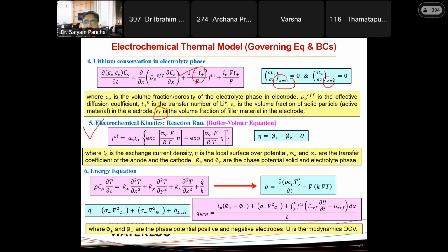And electrochemical kinetics, basically the Butler-Volmer equation, is provided by this equation, and the overpotential is phi s minus phi e minus U, where phi s and phi e are the phase potentials in solid and electrolyte phase, and U is the thermodynamic open circuit potential, and the energy equation is given by this equation, where Q dot is finally